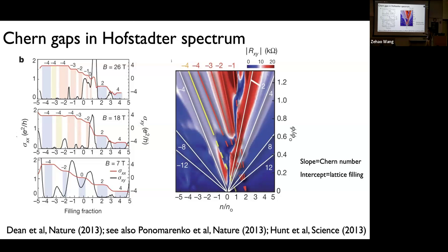And there are ways to characterize this. You can convert the density, knowing for example what the size of the moiré superlattice is. And it turns out that, for example, the yellow line corresponds to a state that looks like the minus 4 quantum Hall state. But in addition to that, you need to add some electrons because you have a periodic lattice. The number of electrons that you add into the lattice is precisely, on average, 1 electron per superlattice site. And for the red one, it's very similar physics, but now you need 2 electrons on average per moiré site.